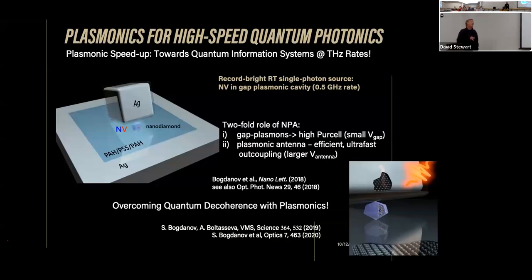So the thing to accomplish here is actually twofold. You'd like to have the gap as small as possible where your emitter is sitting, because it means the volume would be as small as possible, meaning that the Purcell enhancement would be as high as possible. But the cube itself shouldn't be too small, because you need to outcouple your photon. If it is converted into plasmon excitation and sits there forever, eventually it will still go to heat. You need to efficiently outcouple it. And for that, since outcoupling is proportional to volume, it's a dielectric effect, the volume shouldn't be too small.